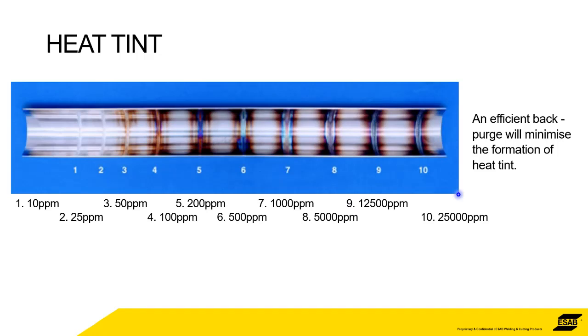Obviously, chromium oxide needs oxygen to form. So if you can purge the area that's getting hot, this is obviously the inside of a pipe, but it's a good illustration. If you can purge the inside of a pipe of oxygen to get rid of the oxygen, then the heat tint won't form. From number 1 at this side, you can see this is 10 parts per million of oxygen, and there's no heat tint, nothing's formed.